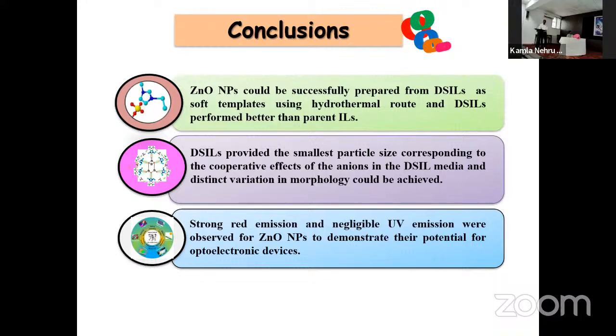So actually, zinc oxide nanoparticles could be successfully prepared from double salt ionic liquids as soft templates using the hydrothermal route, as I have shown, and double salt ionic liquids perform better than parent ionic liquids. These double salts provided the smallest particle size corresponding to the cooperative effects of the anions in the double salt ionic liquid media, and distinct variation in morphology, as you could already notice, was achieved. And strong red emission and negligible UV emission were observed from zinc oxide nanoparticles to demonstrate their potential for optoelectronic